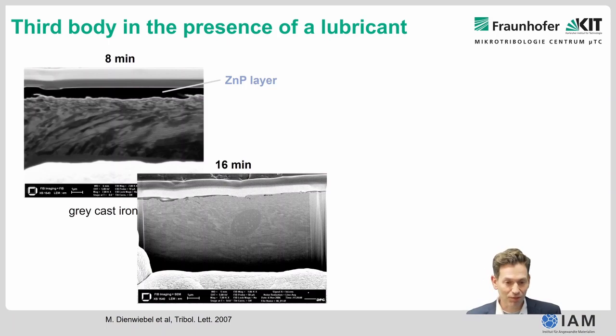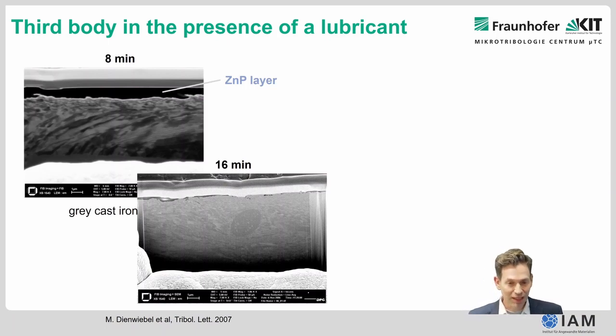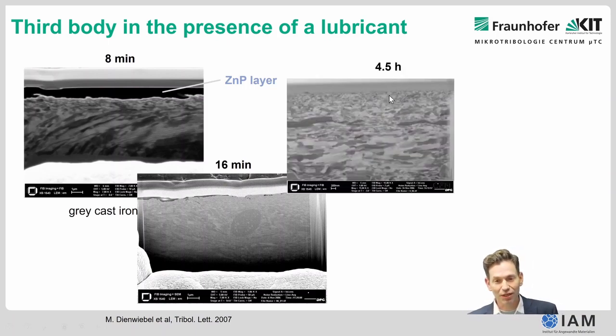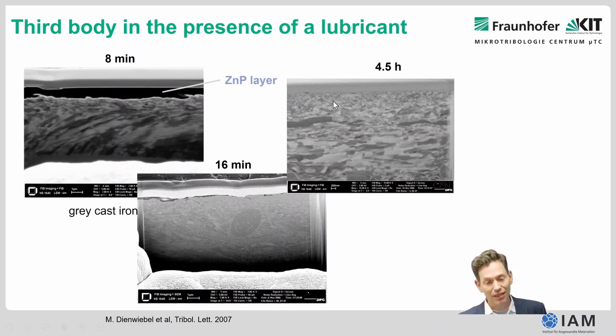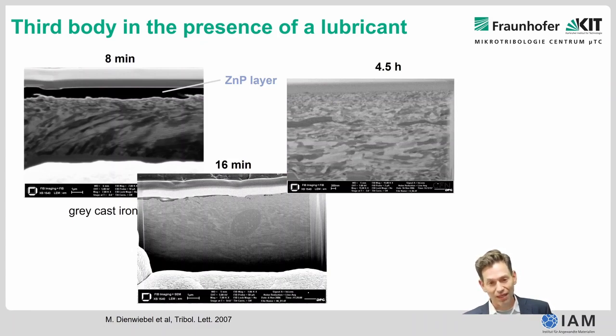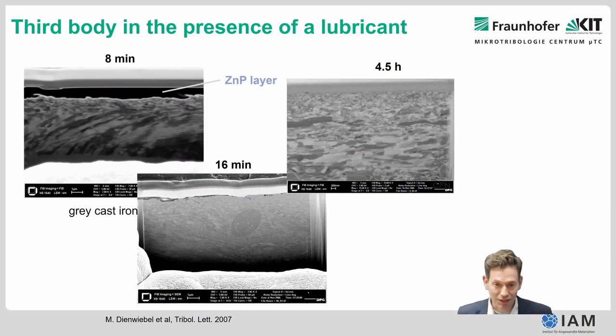That mixing forms the new tribomaterial. If we slide for even longer times — four and a half hours — we see a nanocrystalline homogeneous layer which contains all the chemistry of the lubricant: the anti-wear additives, the friction modifiers, and the other additives from this fully formulated engine oil.